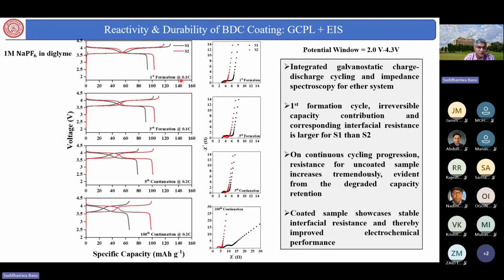You can go from 0.1 C at first formation to third formation to fifth formation to 100th cycle at 0.2 C, and you can see that in the case of S2, red color, the charging and discharging are all maintained, but in the case of black, there has been a decrease in discharging, which shows that there is a decrease. And when we do the impedance spectroscopy, in the case of black color, which is no BDC, there is an increasing polarization resistance. In red color, there is BDC, and there is a small impedance.